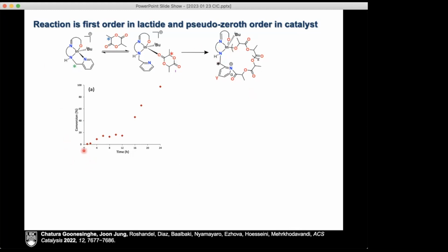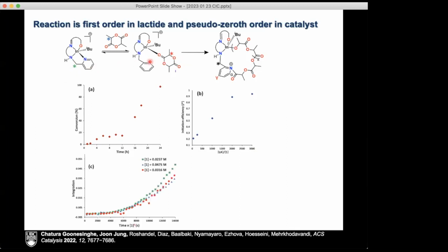So what this looks like is exactly that. Takes a while for us to actually coordinate the lactide. As soon as the lactide is coordinated, there is an attack and then polymerization takes off. We can see that after a while, if you add a lot of lactide, with high equivalents of lactide, we have much higher initiation efficiencies because at some point we really saturate the system and make this, which is the slow step of the reaction, go.